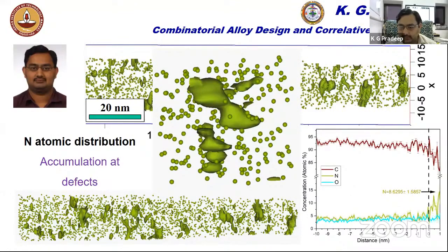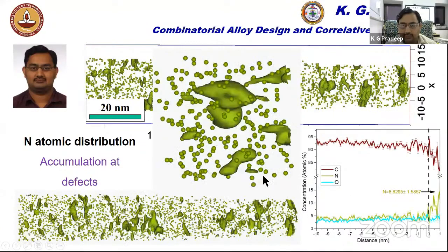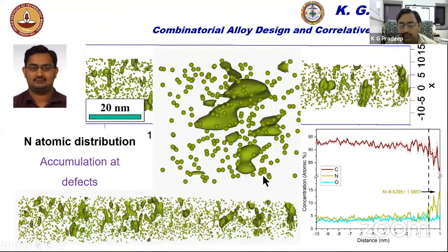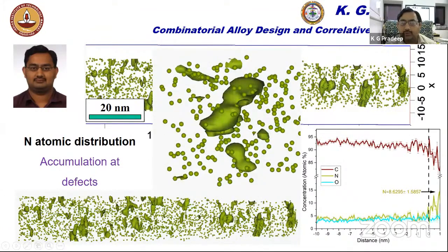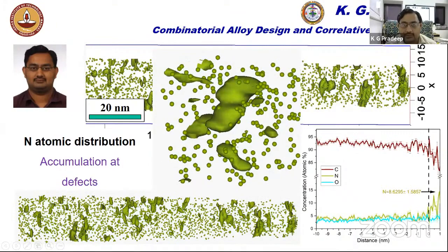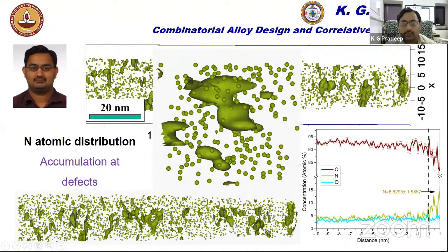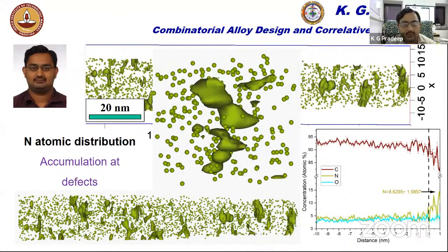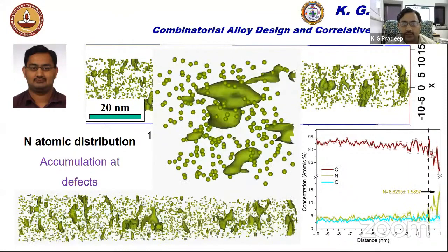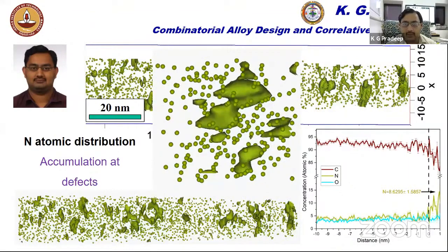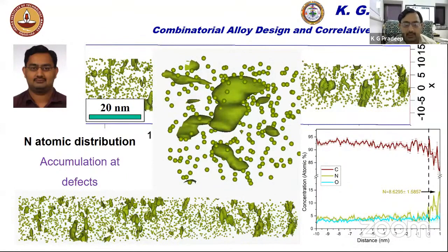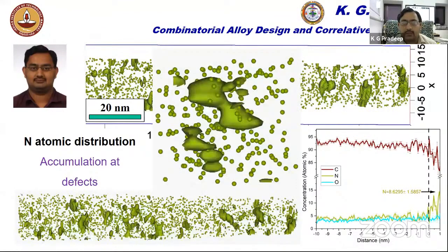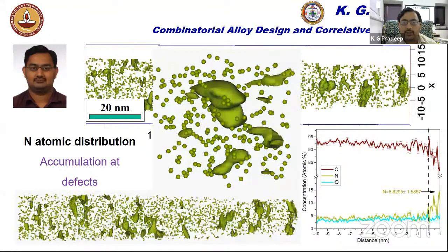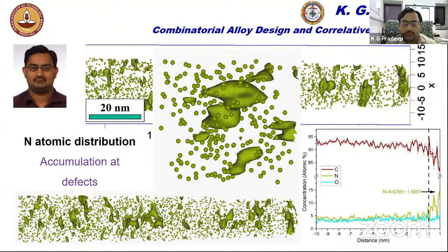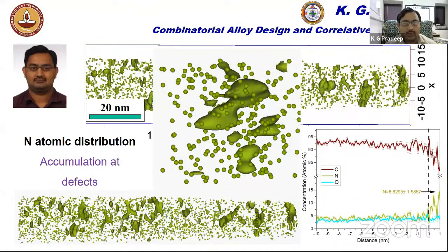So one can even measure how much nitrogen is part of your diamond matrix and how much nitrogen has gone into the local defect sites with their three-dimensional morphology. So we are resolving individual defects at the angstrom level. We are able to see individual atoms possibly in their ideal lattice positions, and we are able to quantify how much of these species are going into these defect sites as well as into their matrix.